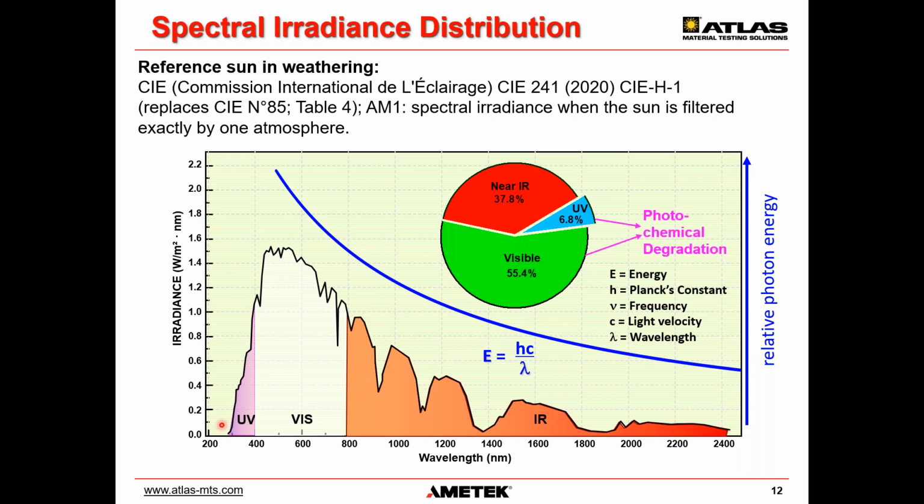However, the lower parts, the blue light, the purple light, the high energy visible radiation can also cause direct photochemical damage. However, the longer wavelength visible radiation and the infrared radiation typically do not cause direct photochemical damage, but can heat up materials.